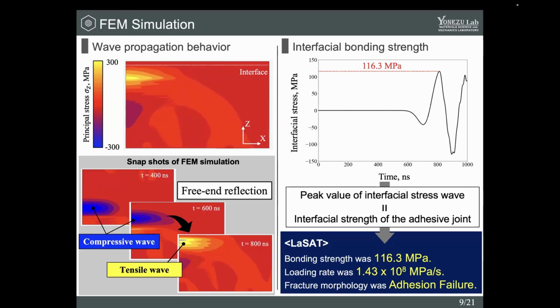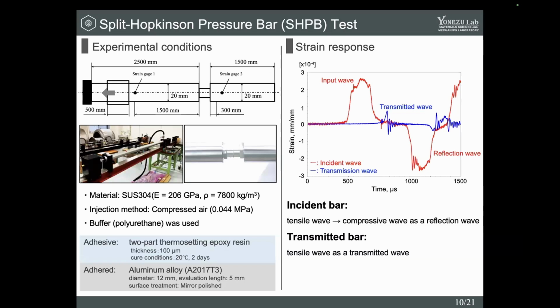This study defines the peak value as the bonding strength of adhesive joints. So the fracture strength of adhesive joints was determined as 116.3 megapascal. And next, to evaluate the loading rate dependency, we conducted SHPB test. SHPB test is commonly conducted as a dynamic loading test.